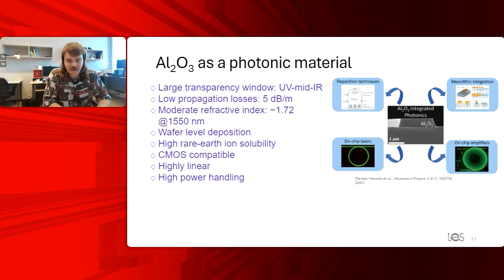It can be wafer level deposited, which makes it very scalable and approachable to clean room technology. As I mentioned, you can pack a lot of rare earth ions in there, in comparison to silicon oxide, where they'll start to cluster and find each other, which happens in an erbium-doped fiber amplifier, which I'll show some comparisons to later. As I just mentioned, it's very CMOS, so complementary metal oxide semiconductor, fabrication compatible. Clean rooms don't hate this material, essentially, and we can use it in a lot of fabrication devices. We also like to add here that it's highly linear. Some people might see this as a disadvantage, but when you are talking about it as a high power amplifier, you don't want any funny non-linearities to come up. So that's a big advantage of working with aluminum oxide, and therefore it also has high power handling.